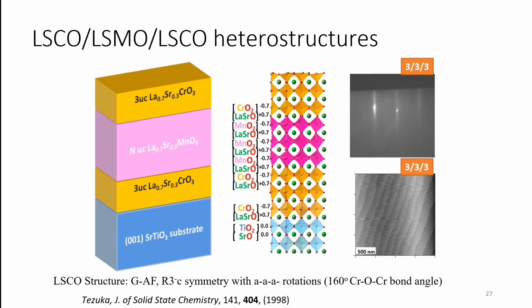So the idea here is that if you have, for example, this manganese oxide layer here, it is going to see a 0.7 charge on top and then 0.7 on the bottom. So there's going to be no net electric field to drive these ions up and down in those layers. So we think that the main thing driving these ions and displacements was just the fact that you have an electric field that moves them around.